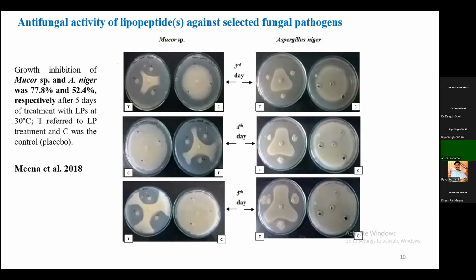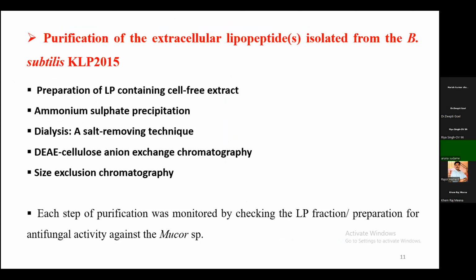Mucor and Aspergillus are both fungal strains which cause disease, especially in plants. The Mucor species causes a disease especially in capsicum, and this completely destroys the plant. In the well diffusion test, 77.8% and 52.4% activity of the two fungal strains was inhibited by this active lipopeptide molecule. After this, the molecule was purified by different techniques.